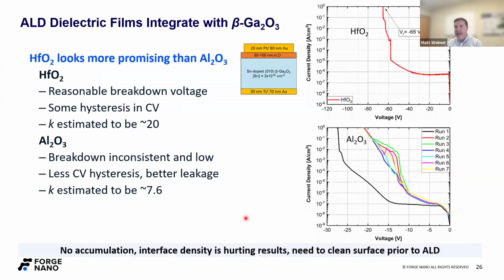And so we started out with a few ALD films, hafnium oxide and aluminum oxide. If we look at the hafnium oxide here, I'm showing the raw breakdown, not normalized for thickness. I'll show that on the next slide. But it looks pretty reasonable. Leakage looks okay. It was a little bit higher than we expected. We estimated the dielectric constant to be around 20. Now, again, all of these metrics are different than we observed on silicon, which is always kind of fun.